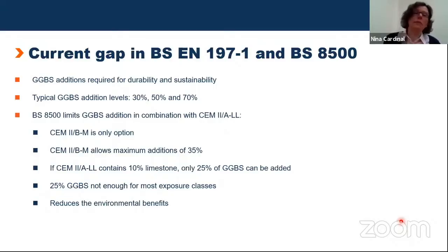But the problem now comes that if you want to combine these additions with a limestone cement, a CEM2ALL, which can contain up to 20% limestone and therefore has a lower embodied carbon than CEM1, you are limited how much additions you can use. So BS 8500 for ready-mix concrete, the only option you really have is the CEM2BM option. As I explained before, a CEM2BM allows a maximum of 35% of additions.